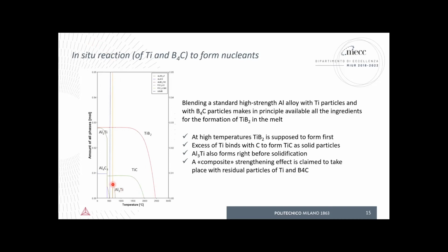Then again, during the solid phase, we're going to have some more Al3Ti, which also precipitates in the solid phase. And in principle, I don't know if it's true under non-equilibrium conditions, we should expect also to have some aluminum carbide right here. But I think it is important to understand the solidification sequence, or what happens in the liquid melt, let's say.